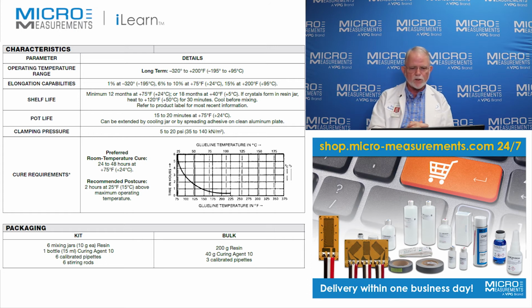Elongation capabilities based on temperature. At the -320, the lowest temperature for this particular adhesive, you can get about 1% strain, or about 10,000 microstrain. At room temperature, it'll go up to somewhere between 6 and 10% strain. As you can tell, you can do a post-yield type study. At elevated temperatures all the way up to 200 degrees Fahrenheit, it's good for up to 15% strain. So depending upon the temperature range, you select the adhesive system and the strain range that you're anticipating your test to go to.